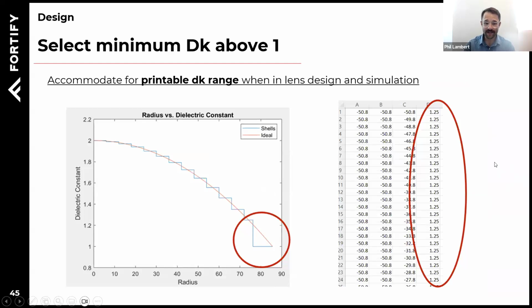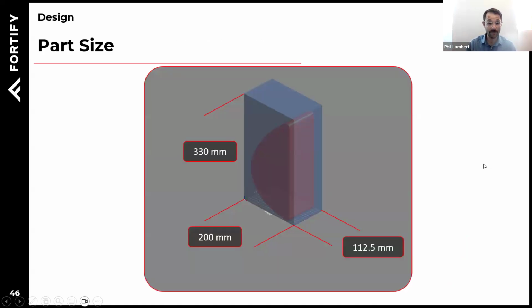And so one important thing I want to make sure people take away from this is that we can't print a dielectric constant of 1. So it has to be above 1, and it has to be within the bounds of our dielectric map that I was showing you just a moment ago, which is why there's that drop down here at the end of our dielectric constant curve. So 1.25 tends to be pretty common in our designs as a minimum dielectric constant. We also have a part size limitation, which we spoke about earlier, but here it is represented. 330 by 200 by 112.5. That's the maximum part size we can 3D print on our printers.